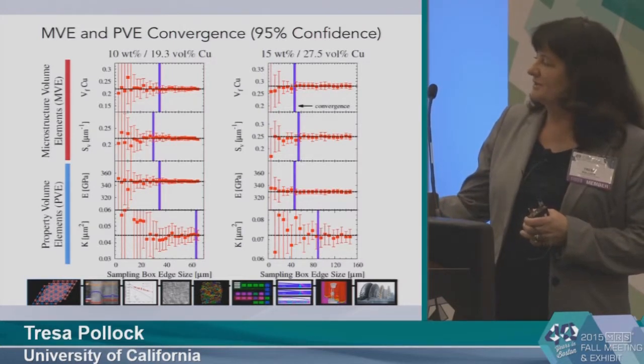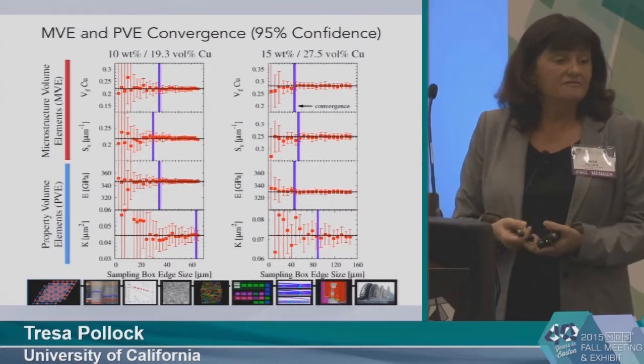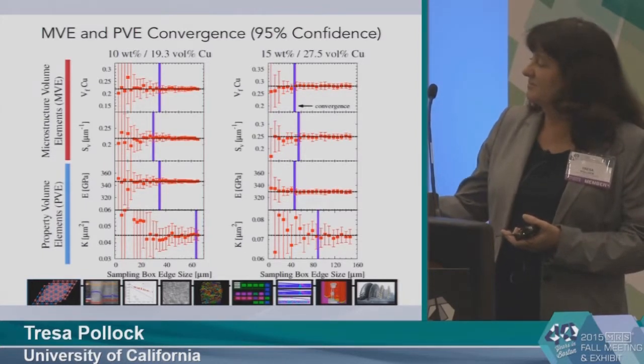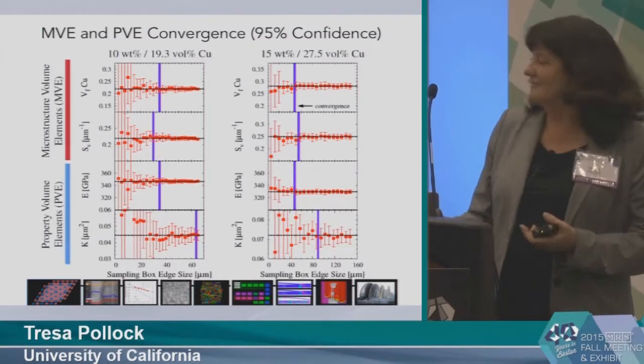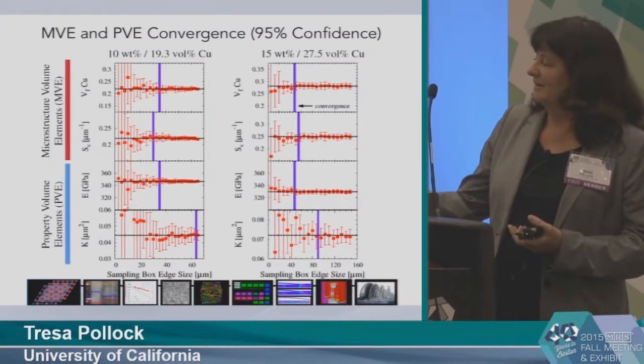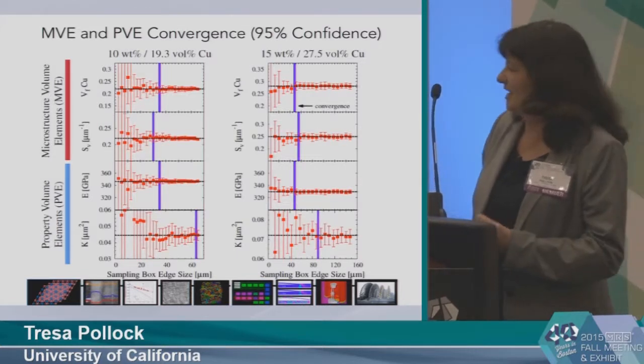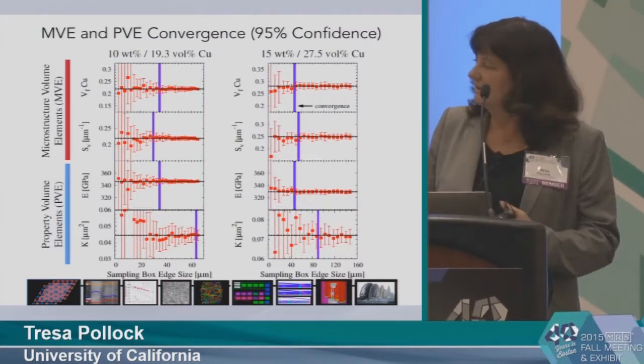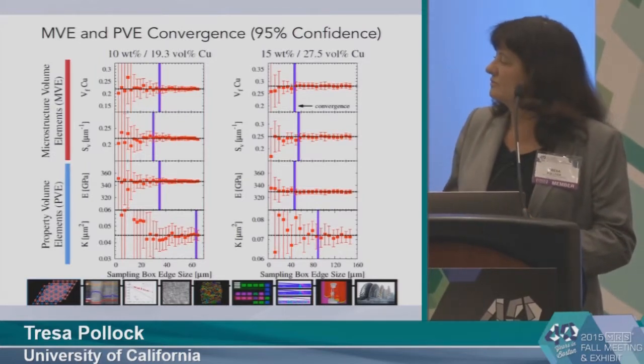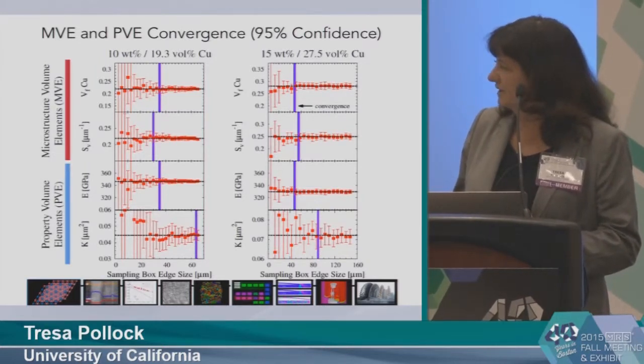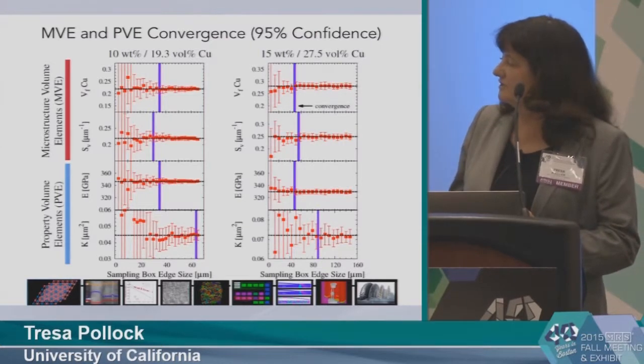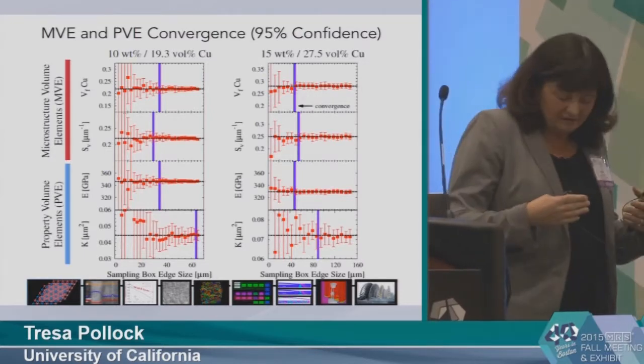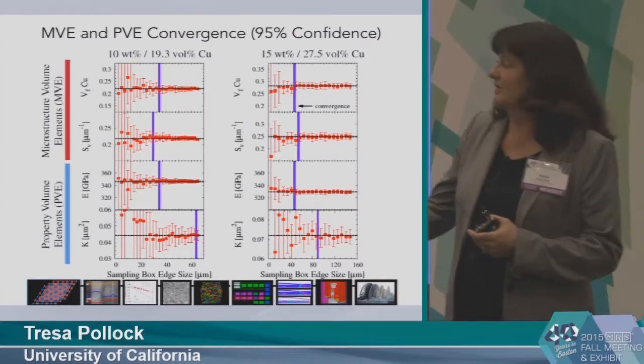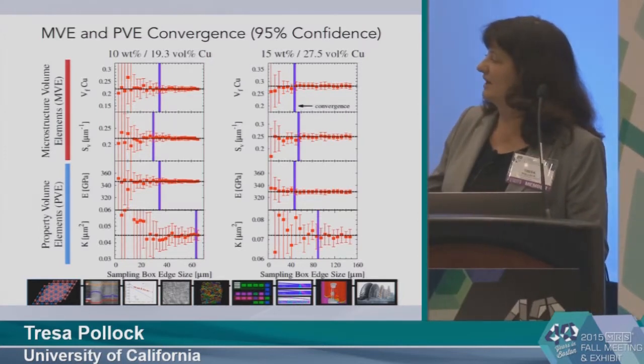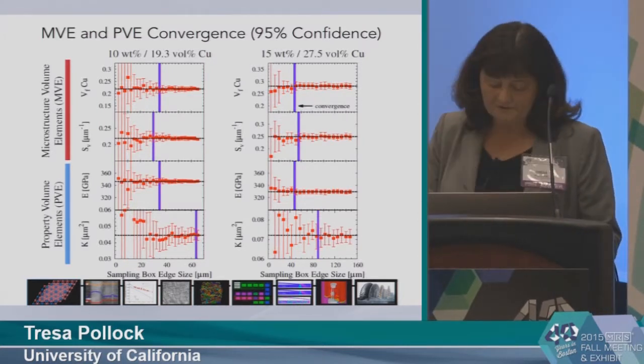And so now we can start assigning properties with some degree of confidence. So I know the modulus of this material will converge at 95% confidence if I sample a box that's 60 cubic microns, for example. And so it gives new ways of trying to be more quantitative about what we're doing with the materials. And so you can do this for properties. You can also do it for aspects of microstructure. And so in these sorts of systems, you have to converge everything, right? You have to converge the microstructural features as well as the property features.